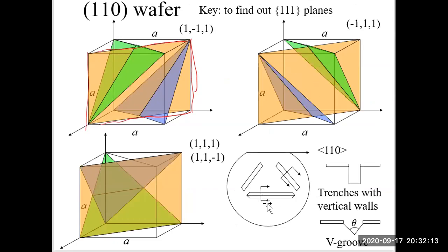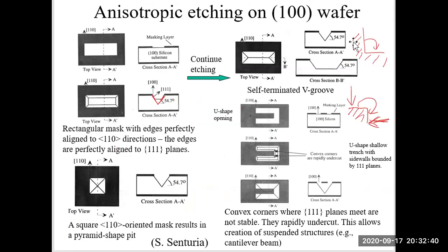And in addition, we can also fabricate V-shaped trenches with slanted side walls on 110 wafer. But please know that we are able to fabricate V grooves on 100 wafer as well. And we can calculate this angle, right? This angle will be equal to 180 degrees minus 2 times 54.7. That's the angle theta of the V groove fabricated on 100 wafer.